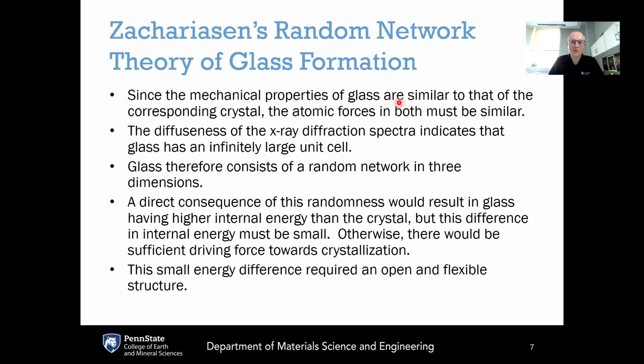So the mechanical properties of a glass are similar to the mechanical properties of the corresponding crystal, so the atomic forces in both must be similar. What this means is that the bonding between atoms would be more or less similar between the crystal and the glass. So if we consider silica, for example, the bond that is relevant is the bond between the silicon and the oxygen.